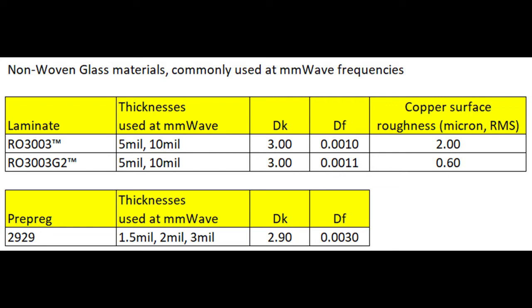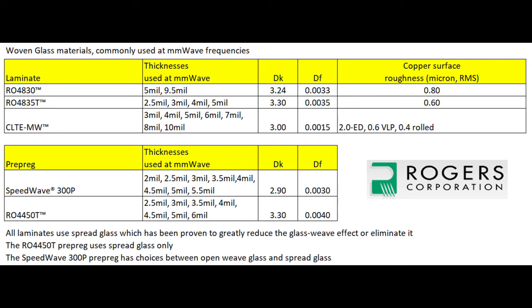The next picture shows thin materials that have glass reinforcement — still thin laminates and prepregs, but with woven glass layers. The first is the RO4830 laminate, available in 5 mil and 9.5 mil, DK 3.24, DF 0.0033, and copper surface roughness of 0.8 microns — pretty smooth. To give a guideline: very smooth rolled copper is about 0.4, so 0.8 is rougher than that, but 2.0 microns would be considered quite rough.